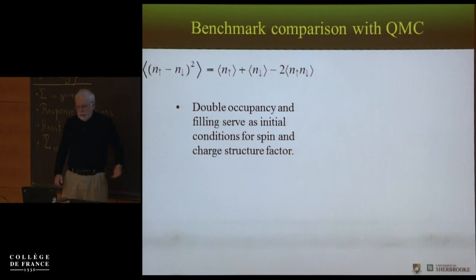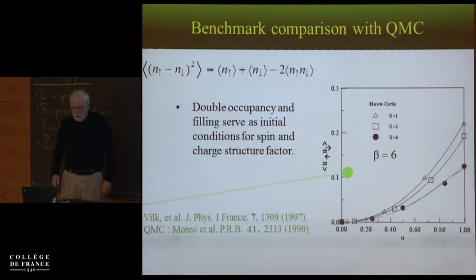Double occupancy is a very important quantity in this approach, and if you plot double occupancy as a function of filling, for U equals 1, 2, 4, at half filling, it's beta equals 6, but you see that, again, the quantum Monte Carlo points fall directly on the TPSC. And if we had done Hartree-Fock factorization, then this would be independent of U, and there's clearly a dependence on U.